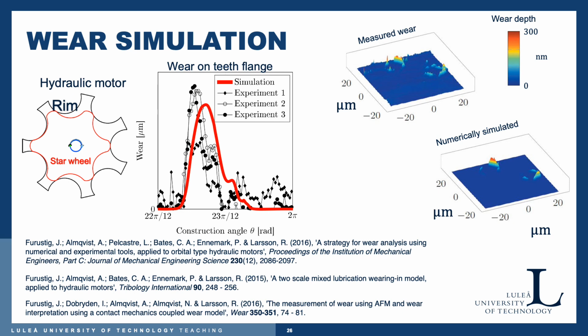So there is a certain wear depth, you see 0.3 micrometer here on this very small patch, and these are very small marks, as you can see. Then he also simulated the same thing, and he found very similar wear, numerically predicted, as he had observed in the experiments.